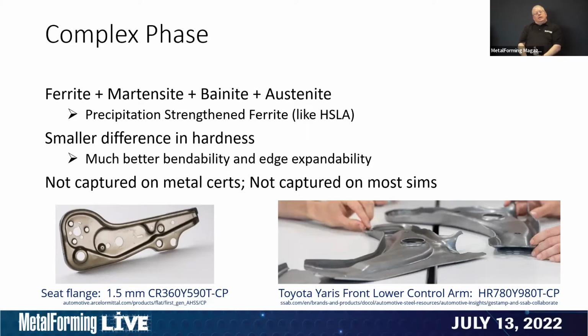And the reason for that is, well, from the name, complex phase, there's combinations of every metallurgical phase in there, depending on the strength level, depending on the steel maker. But the ferrite, which in dual phase and TRIP steels is super soft, steelmakers have figured out a way to make that ferrite actually much harder. And so what we have in complex phase steels is a microstructure that is of a more uniform hardness. That leads to higher yield strength at a given tensile strength, but that also helps when trying to expand cut edges. So as shown with the examples that are on the screen now, the complex phase steels are best applied to parts that have the cut edges that are expanded.